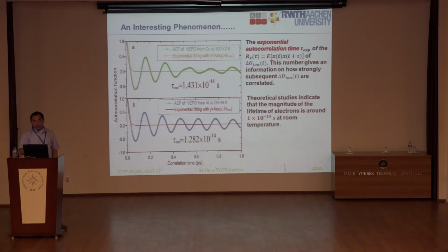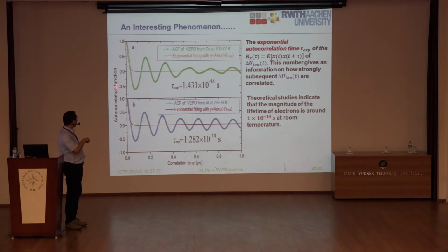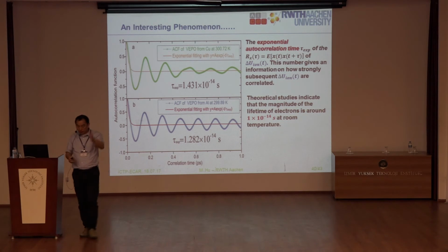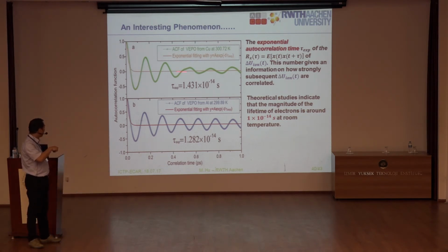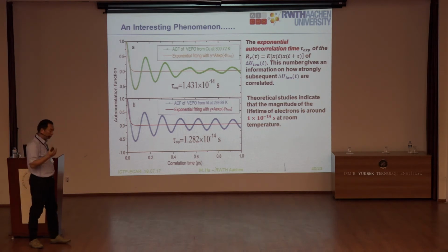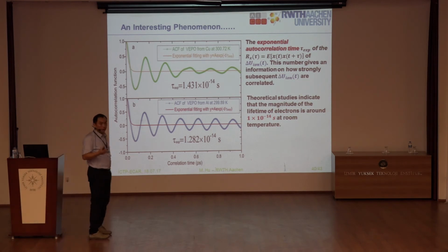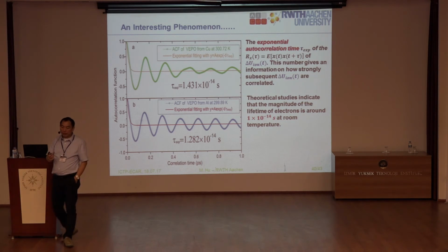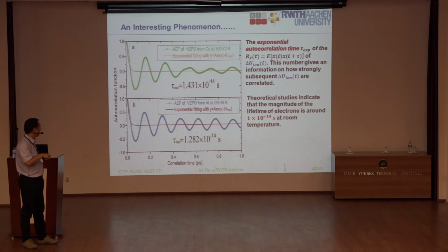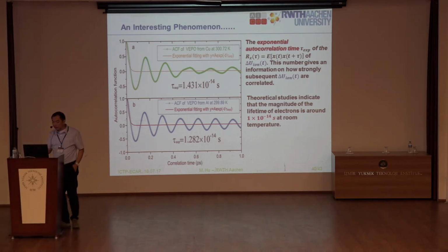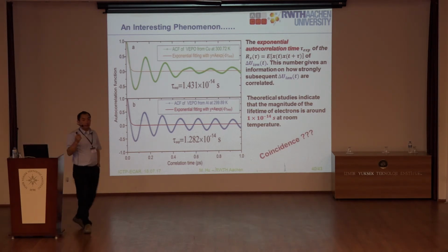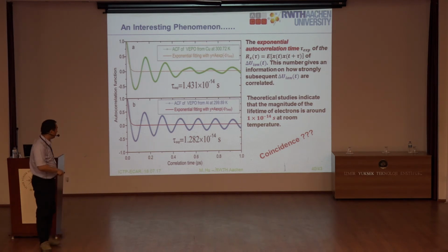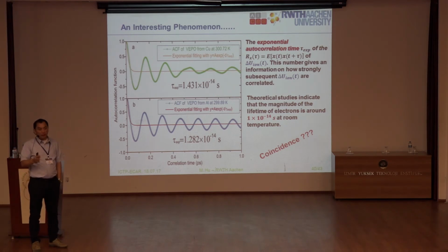Another interesting phenomenon is that we can also calculate the autocorrelation function of this electron potential oscillation. And then we found that in space, actually, you also get this decay. This is the original data, and then we fit this with an exponential decay. We found that this exponential decay gives a characteristic time of about 10 femtoseconds, which is very, very close to the relaxation time of electrons in pure metals, as accepted in lots of literature. But of course, right now, we cannot prove that this is the real relaxation time of electrons. So we just found that this is a very interesting phenomenon, and we are still working on that. And in case you have any ideas about this, we can have some collaborations, and I'm quite open to this. We are not sure if this is a coincidence or some other mechanism inside.